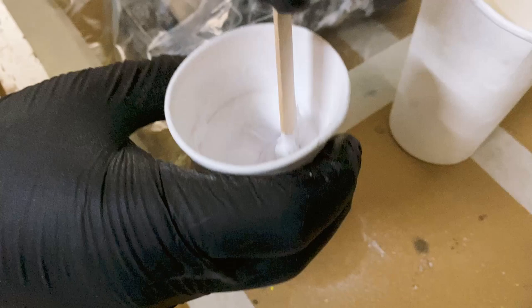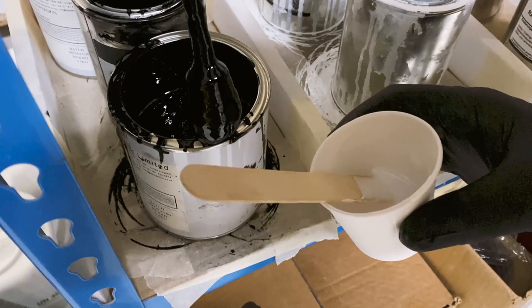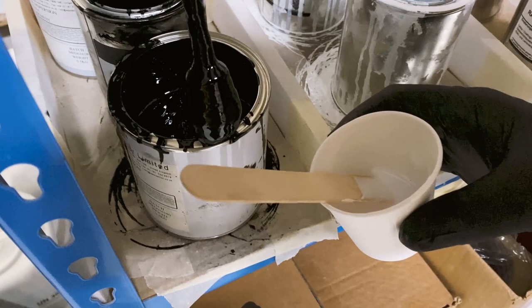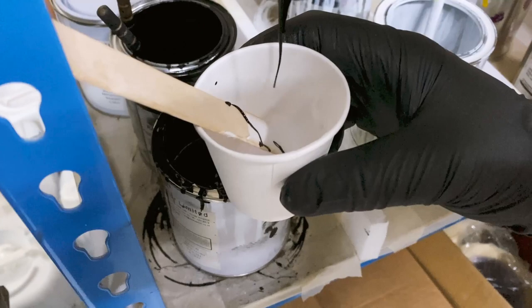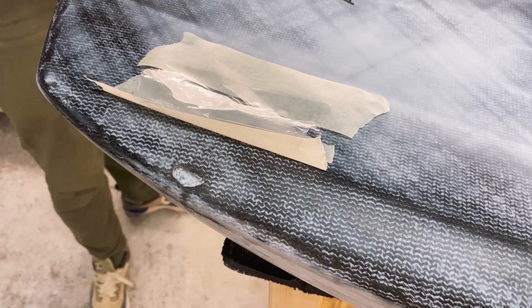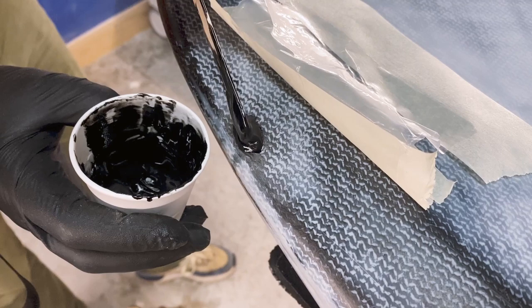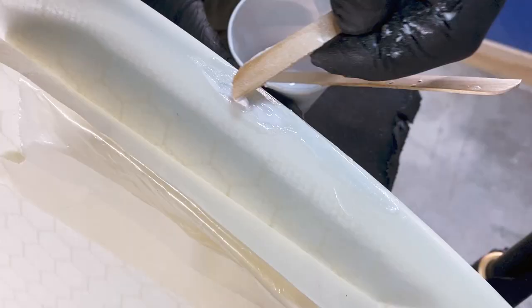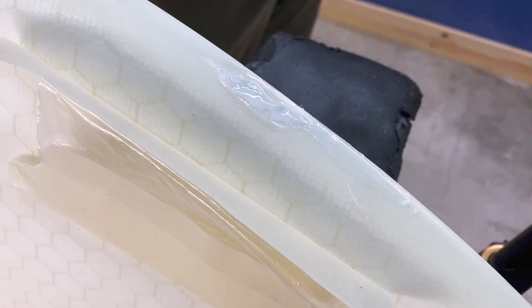In this case we're looking for that yogurt-like consistency, maybe a bit thicker so it stays in the hole better. For the carbon filler, add some black pigment — a white repair in a black board doesn't look nice, so a few drops of pigment makes it match. Now smear the epoxy into the hole, making sure you really push it into all the cracks using your finger or a wooden stirring stick. Make sure the epoxy is all the way in there, then slightly overfill the top of the hole just a little more than needed.